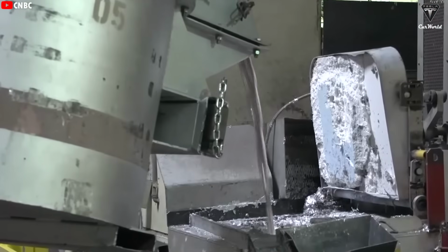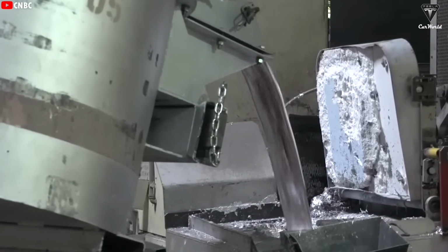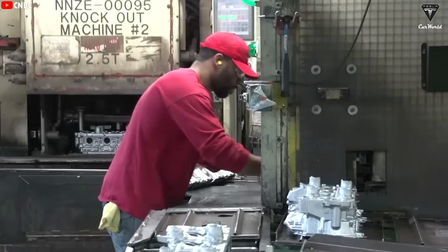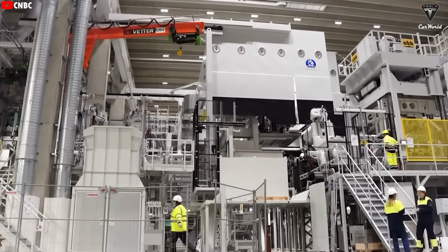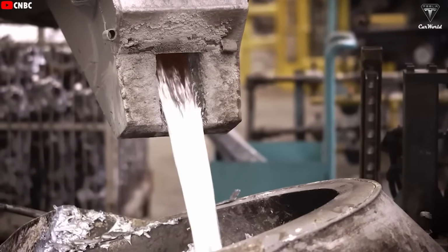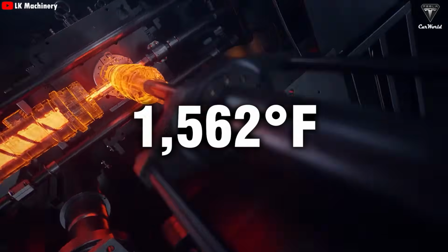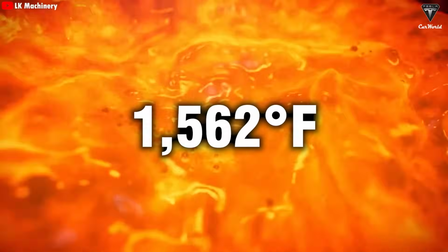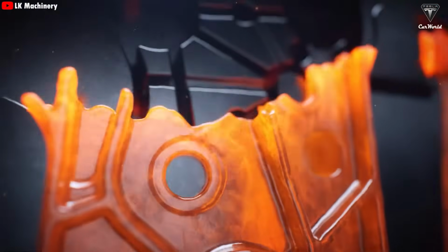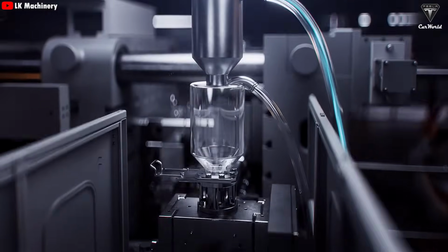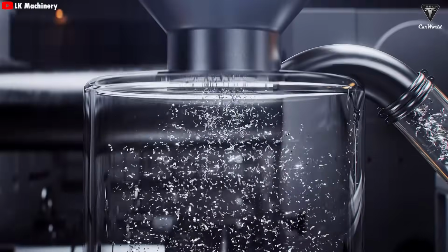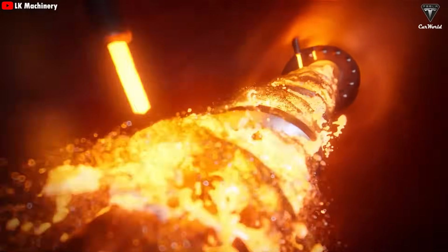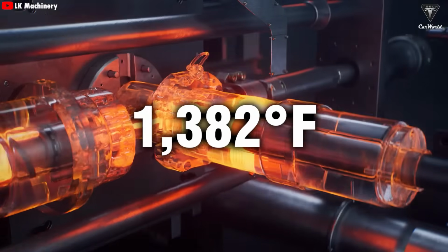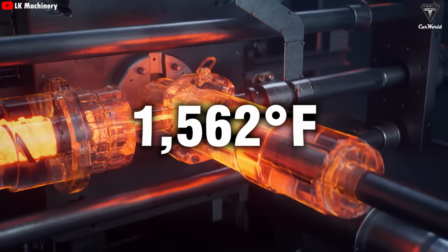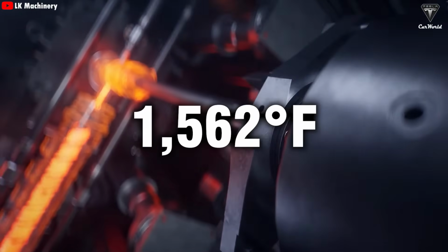The process begins with material preparation. Tesla melts down fresh aluminum ingots along with recycled aluminum from previous casting cycles in a furnace, reaching temperatures around 1,562 degrees Fahrenheit. Once molten, surface impurities are removed, and the purified liquid metal is transferred through heated pipelines into a sealed holding furnace, where temperatures are maintained between 1,382 degrees Fahrenheit and 1,562 degrees Fahrenheit.